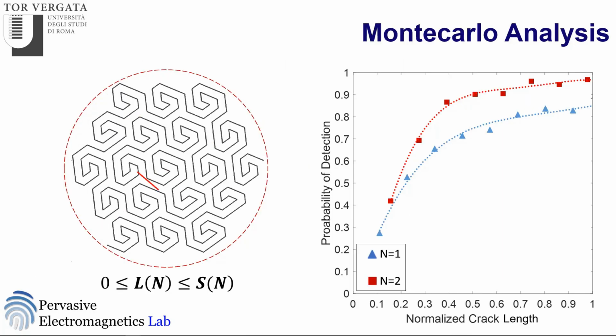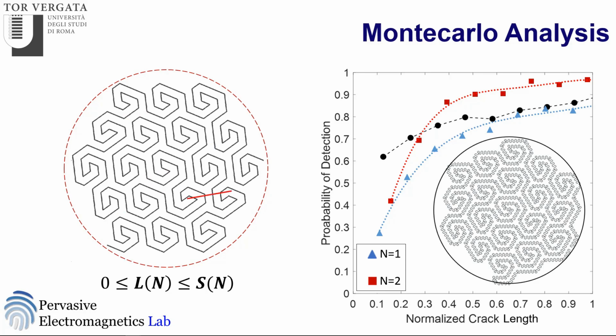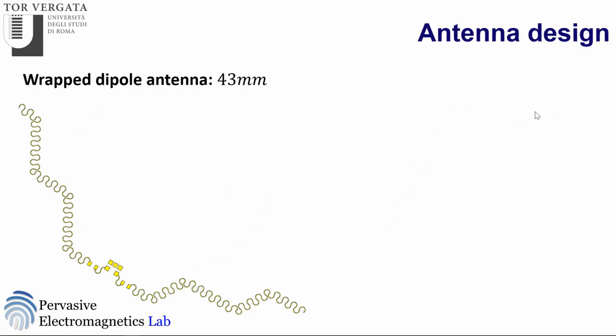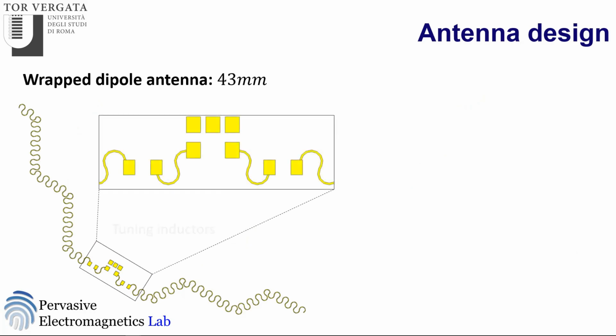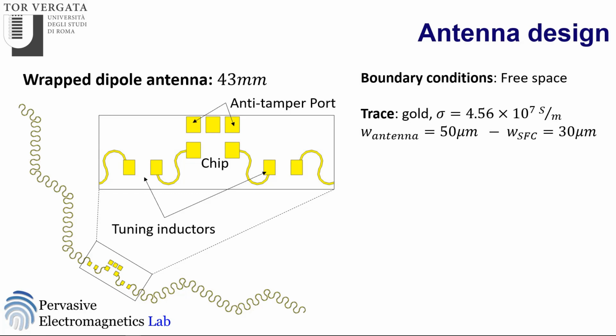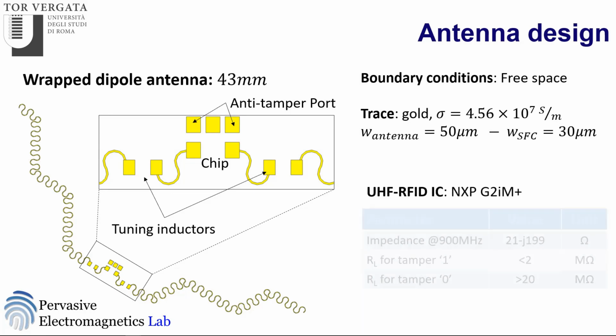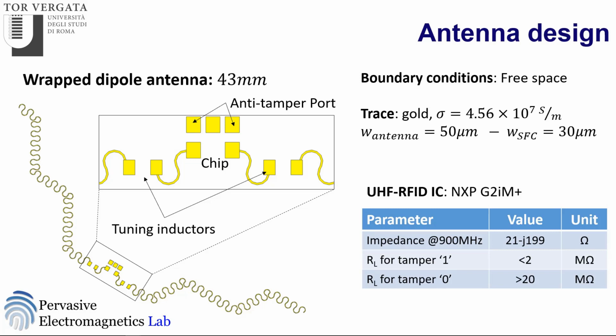But we have some advantages. In fact, if we take the Monte Carlo analysis and consider the modified stretchable curve, we have an increment of probability of detection for cracks that are less than half length with respect to the normalized crack length. The radiating element is a dipole antenna that can be tuned by 2 inductors. The electromagnetic analysis has been done considering free space conditions.